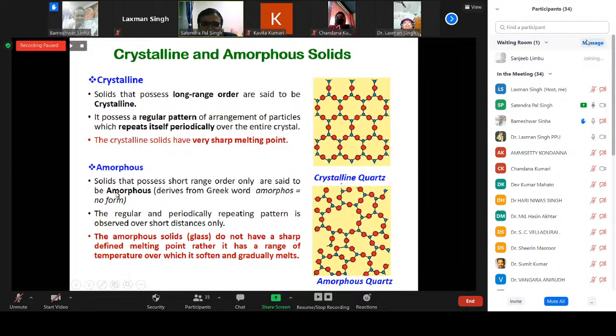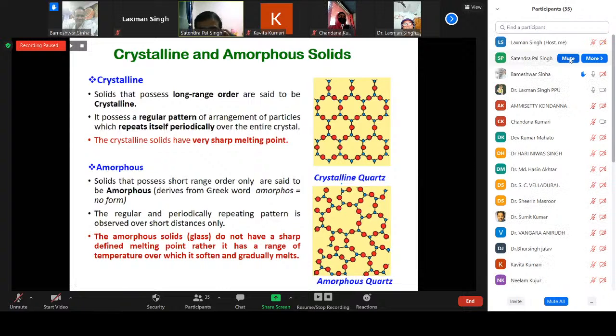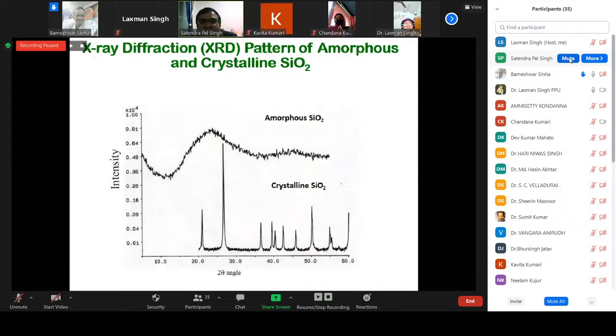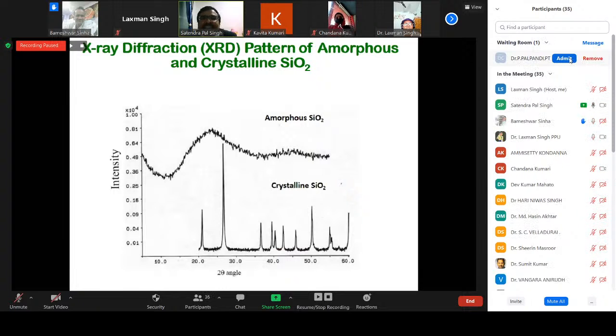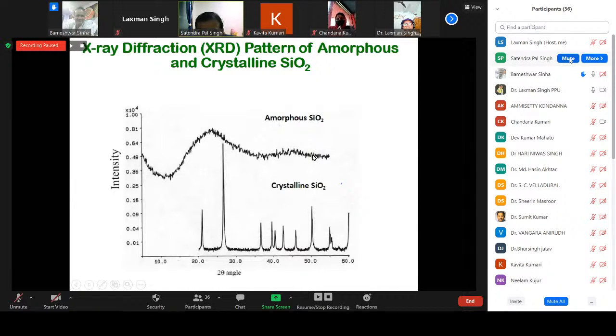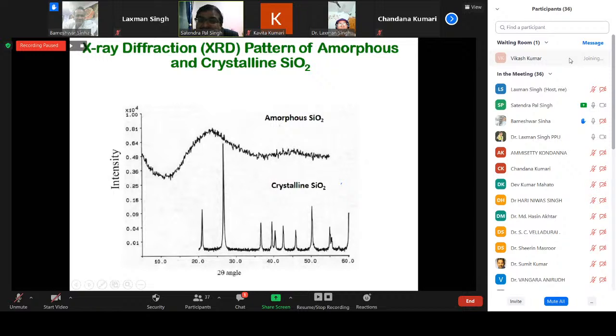The terminology amorphous derives from the Greek word amorphous, that means no form. It's formless. It's a short range ordering. And if you measure the X-ray pattern of the amorphous and crystalline silicon dioxide, you'll have the XRD pattern something like this. We have a very broad hump for the case of amorphous silicon dioxide, and the crystalline quartz will have very sharp peaks.